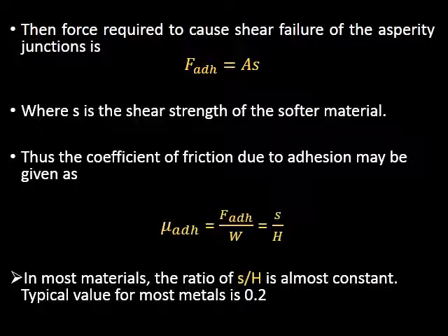From the experiments that have been performed, we can see that the friction coefficient actually depends on the counterface or the meeting materials. And also under normal atmospheric conditions, the actual values of the friction coefficient, especially for metallic materials, are generally found to be in the order of 0.5, but this theory predicts a coefficient of friction as 0.2.